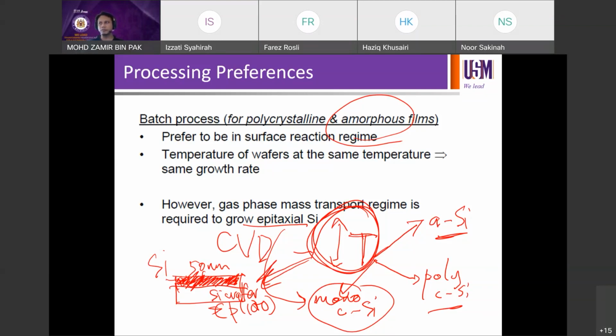Because you can also use, for example, your CVD to deposit amorphous silicon on monocrystalline silicon. You guna wafer yang sama juga. But then you can tune the process, usually low temperature, to deposit 50 nanometer of silicon, but that particular silicon can be amorphous silicon. Dia tak semestinya monocrystalline silicon or polycrystalline. So tengoklah nak apa. Kalau if you go for heterojunction, kalau if you talk about silicon solar cell, for example, specifically, dia pakai silicon wafer monocrystalline (100).